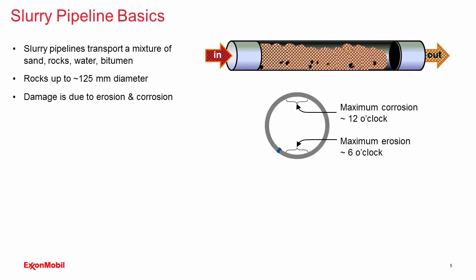There's damage going on inside the pipeline, and specifically at the 6 o'clock position, we have maximum erosion, and that's where the erodent material, the sand, the rocks, settles, bounces along the surface of the pipeline, and removes material. Now, that erodent material doesn't contact so much the 12 o'clock position, so we have primarily a corrosion mechanism that is dominant there. There's water, there's oxygen inside the pipeline, so certainly there is corrosion.